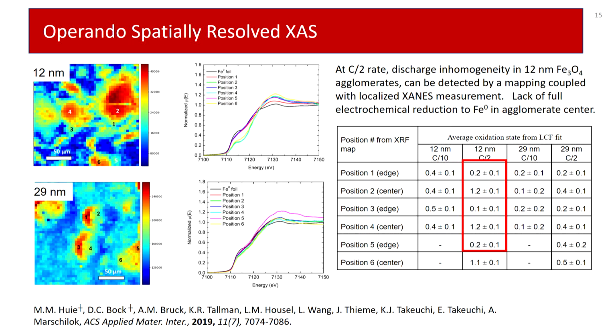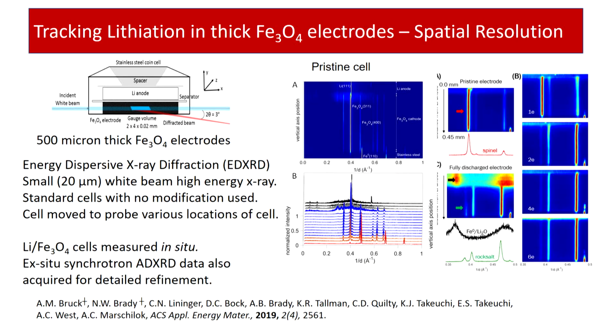With the small crystallite materials, there's a difference during the operando reduction process in the oxidation state of the iron at the surface of the aggregate versus the center of the aggregate. But for the 29 nanometer material, there's much less difference, meaning that those agglomerates are porous enough to discharge fairly uniformly, which gives us insight into why the parasitic heat is higher for the larger material.